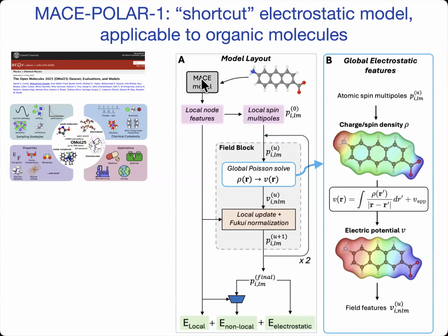So it starts with MACE, the two layers of ACE expansion, but then in addition to that, we predict multipole moments, and from the multipole moments, we get a field. From the field, we recompute the multipole moments. So we predict new updates to the multipole moments based on the local field, and we do this twice, and the final multipole moments are then used to compute electrostatics and the correction to the energy based on the field features, field and multipole features. So that's the essence of the model. It has electrostatics explicitly built in. When you go from the predicted multipoles to the field, you solve the Poisson equation.